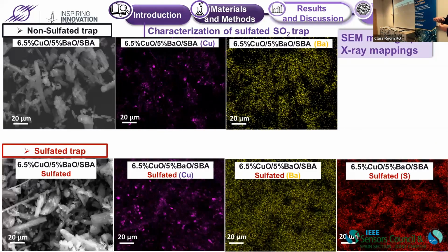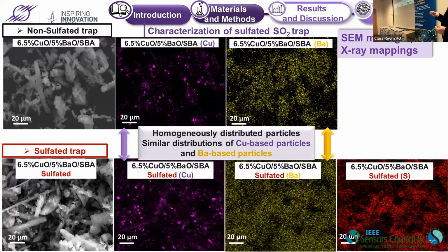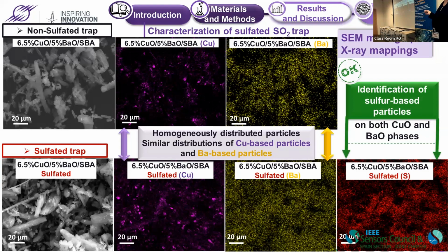Here you can see SEM micrographs and X-ray mappings of the non-sulfated trap at the top, and of the sulfated trap here. You can see that the copper-based particles and barium-based particles are homogeneously dispersed before the test and also after the sulfation. There is no modification of the dispersion after sulfation. And if you look at the S element here, there is sulfur in the trap. So we identify sulfur-based particles on both the copper oxide and barium oxide phases.